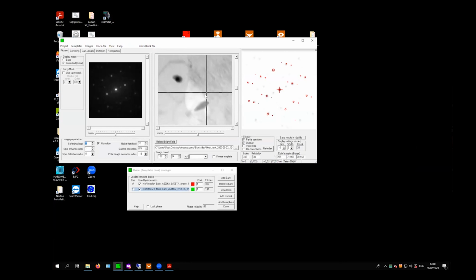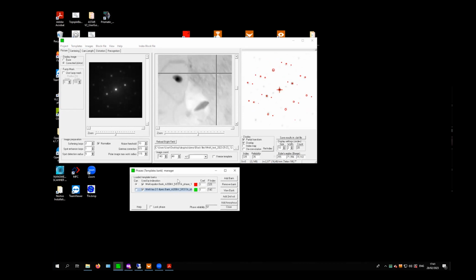And just to orient yourself again here in the center, what you can see is the inclusion, or that secondary phase that is formed in the sample. And basically, as I drag the cursor over this data set, here on the right, there's already a diffraction pattern. It's just inverted in contrast being shown. And at the same time, this overlay in red or green is already a live matched template. So Thanos explained this, that we basically go from the crystal structures that we expect for this sample. We can load these crystal structures as templates down here in the template manager. And basically, the software is doing the fitting of these templates live as I drag across here.